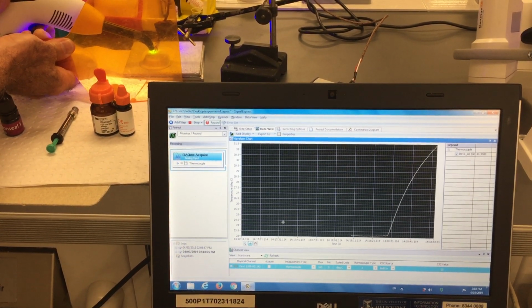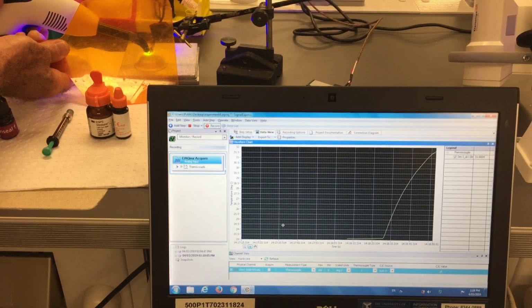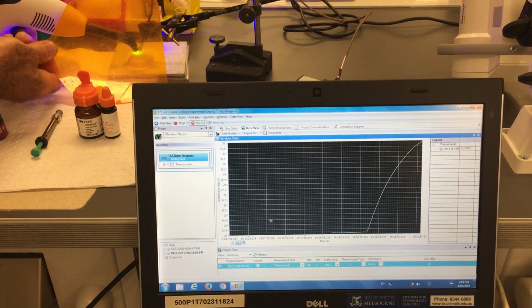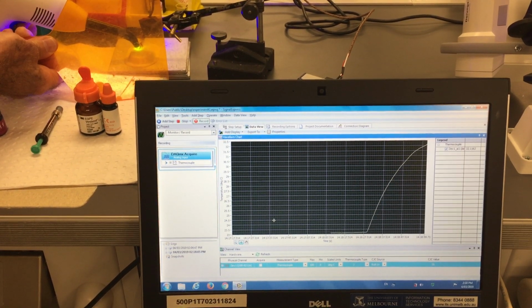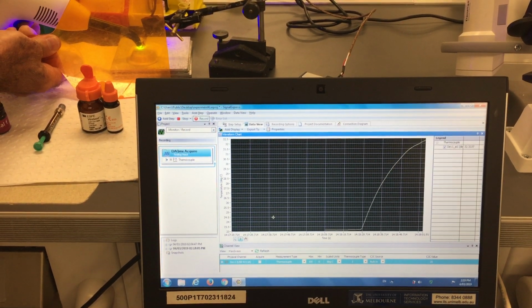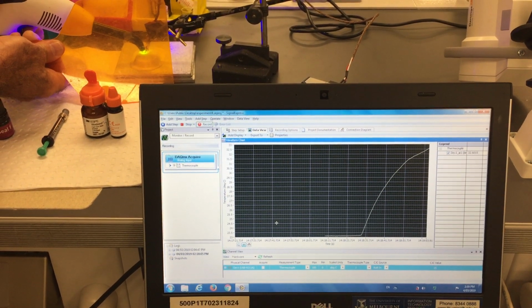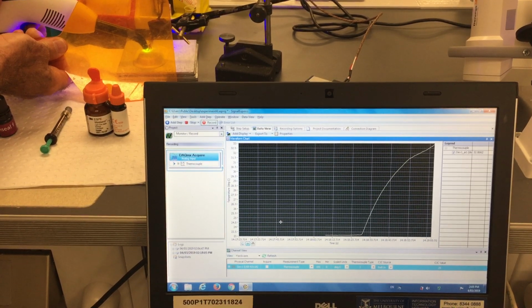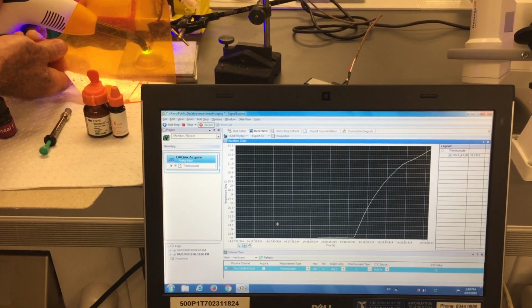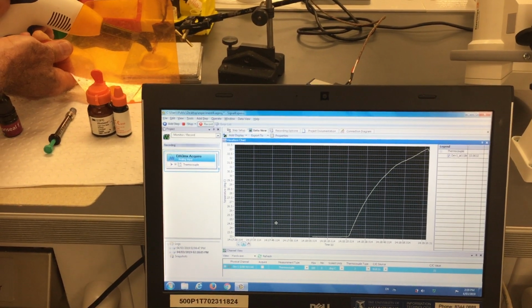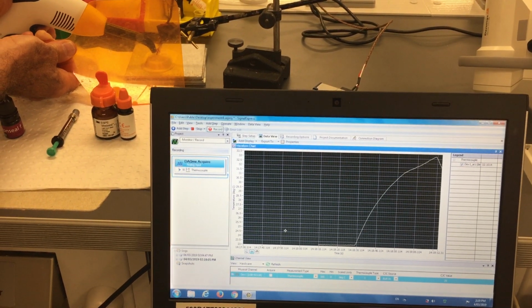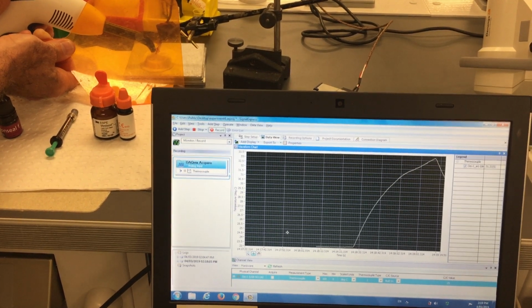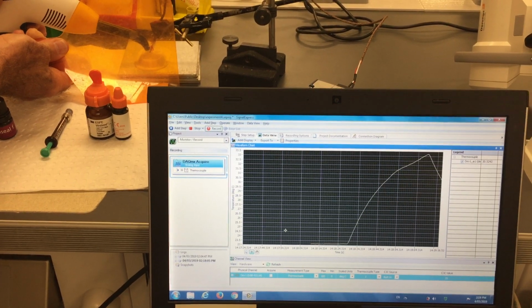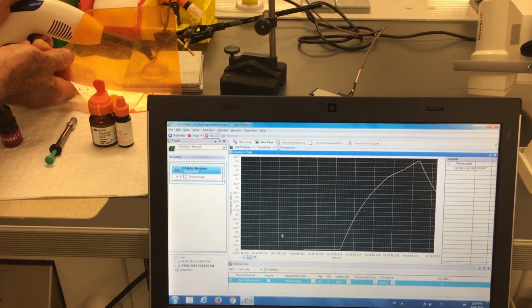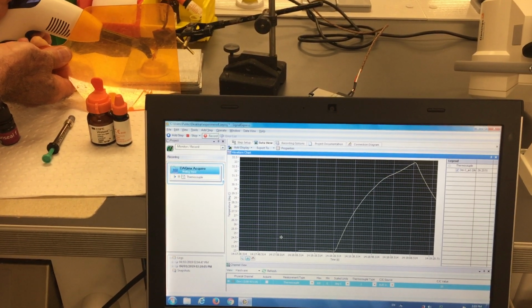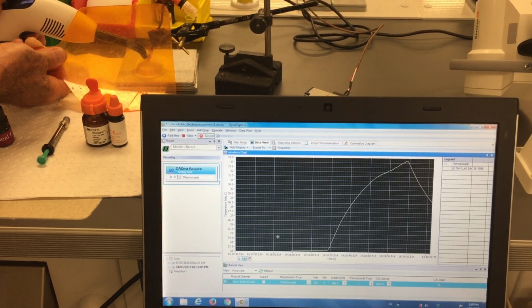Now this is where one of the things you need to be careful with light curing units. The new powerful light curing units will only require you to cure for 3 seconds. They're trying to decrease the amount of clinical time you need to take to cure materials, but you must be aware that the energy they put out in 3 seconds is equivalent to something this older light curing unit puts out in about 20 to 40 seconds.